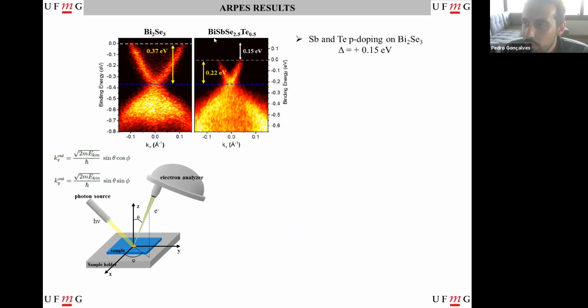When we put antimony, we lose the effect of the topological insulator. But when we put tellurium again, we can retrieve the curve here, and now we have a topological insulator again. That's why we try to use these different effects to see the quantity of each element that can be used to retrieve what we had before. I see. So you wanted to move the Fermi level to the Dirac cone level, right?